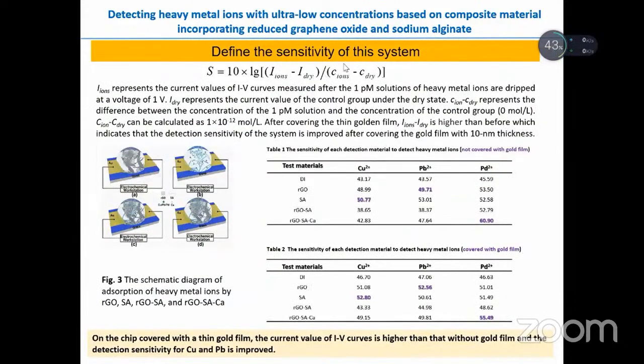Next, we define the sensitivity of this system using this equation. There are 4 different types of configurations. That means we use different materials. The first is RGO, then SA, RGO and SA, and RGO, SA, and calcium ion. Here there are 2 tables. The first table is the calculated sensitivity of each detection material. Here it's not covered with gold film. We can see that with different test materials, the calculated sensitivity is different. The second table shows the sensitivity of each detection material covered with gold film. On the chip covered with the thin gold film, the current value of the I-V curves is higher than that without gold film, and the detection sensitivity for copper and lead is improved.